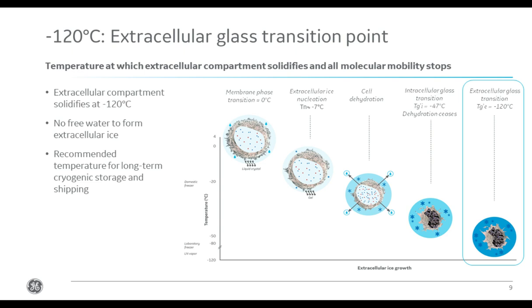However, this is a volume-dependent figure. At that point, cells will start to dehydrate, and this will continue as the temperature falls further. After controlled optimized cooling to minus 47 degrees, the cells will be maximally dehydrated and can safely be transferred to long-term storage, which must be below minus 120 degrees to ensure long-term stability for DMSO-based systems.